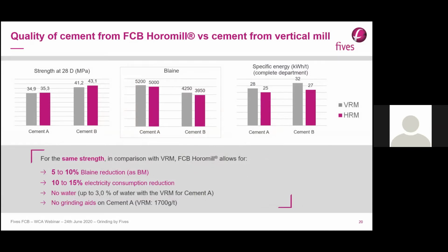The comparison can also be done in terms of quality with a vertical roller mill. And in this typical case, the observation is similar to the one we can do with a ball mill. I will not come back to the savings in terms of specific energy that are here in this case between 10 to 15%. But it's also important to note that the quality in terms of strength development, it means the quality of the cement that cement manufacturers sell, is reached and obtained with lower Blaine for Horomill compared to vertical roller mill.